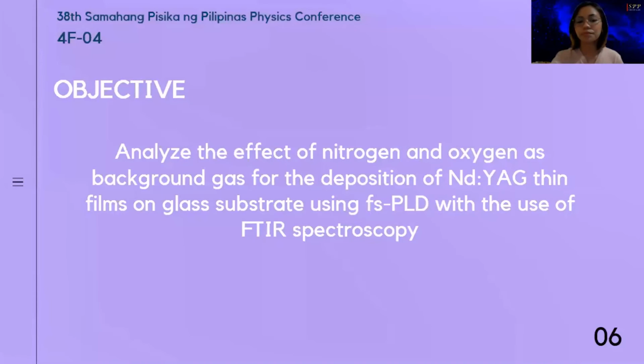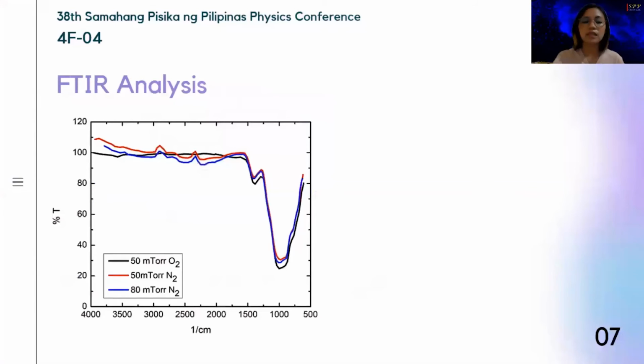In this paper, we analyzed the effect of nitrogen and oxygen as background gas for deposition of Nd:YAG thin films on glass substrate using femtosecond pulse laser deposition with the use of FTIR spectroscopy. This is the FTIR analysis of the deposited films under the influence of oxygen and nitrogen gases.